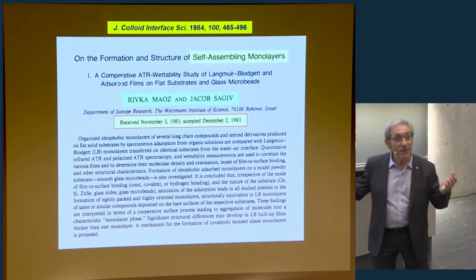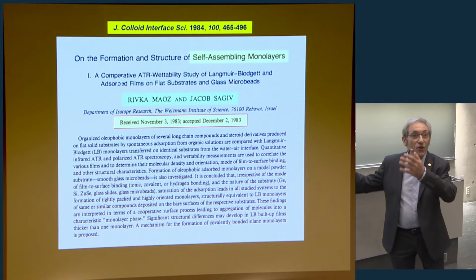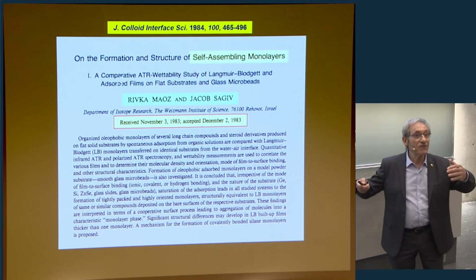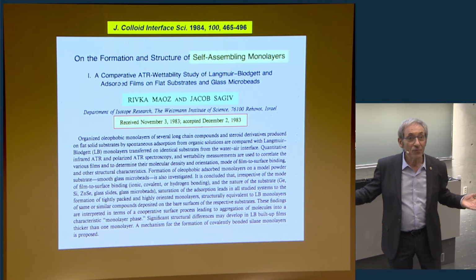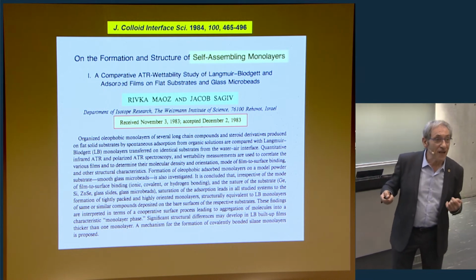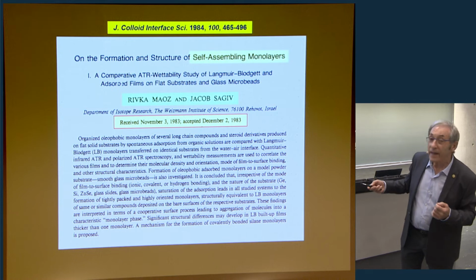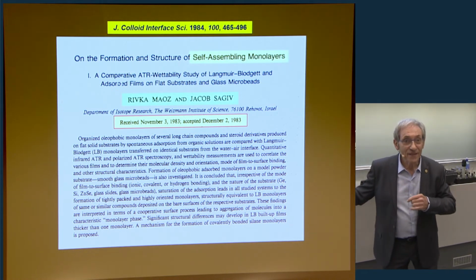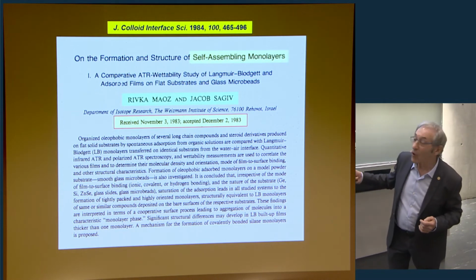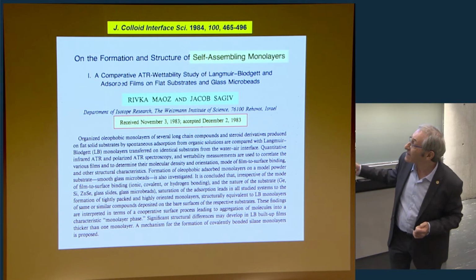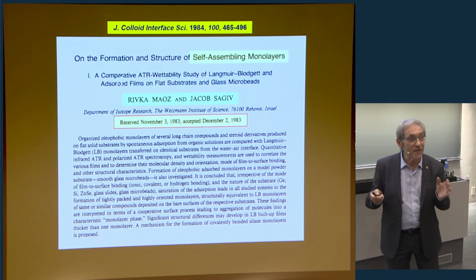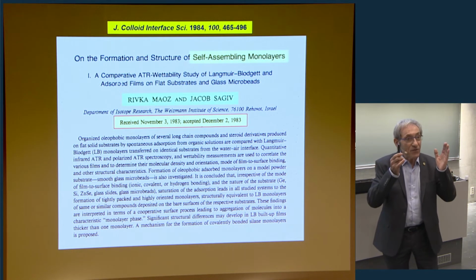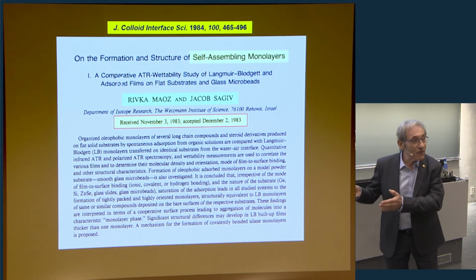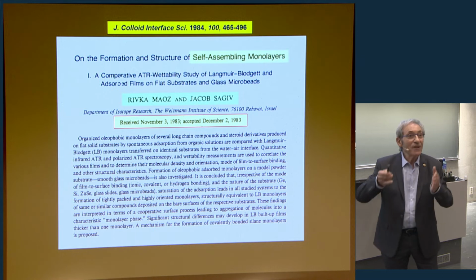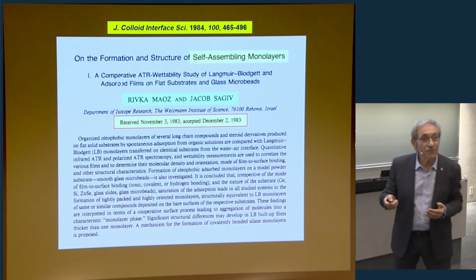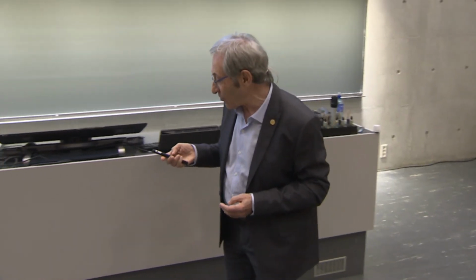I have not mentioned previously that we also invented here the methods of characterization. When we start making monolayers and multilayers, how do you know what you have here? So we used infrared spectroscopy for the first time in a quantitative manner, in a different way than Dave Allara developed it, as we heard from the previous lecture. We characterized our monolayers by direct comparison with Langmuir monolayers that were known and have well-defined structure. So the infrared was applied to our self-assembled monolayers in parallel with Langmuir monolayers. They were the standard versus which we could decide what structures we have on our surfaces.